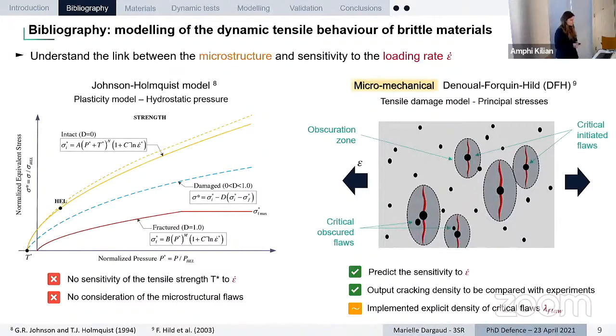or defect in this obscuration volume cannot be triggered anymore because of this local drop of stress. Very good points of this model are that it can predict the sensitivity of the tensile behavior according to the loading rate. The output of the model can be compared to some experimental data. And most of all, there is an implementation of an explicit density of the critical flaw population in the material. However, this last point might present some limitations that we will go deeper into later in this presentation.